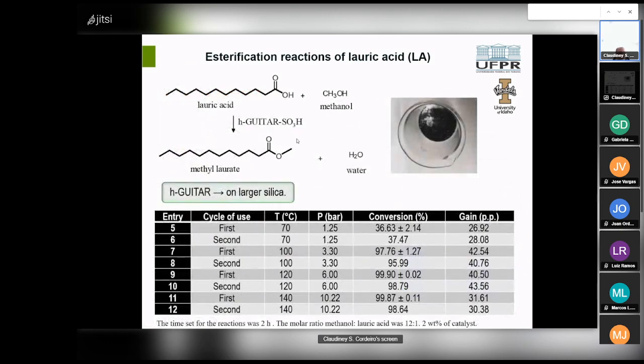After the first cycle of use, the catalysts were recovered, regenerated, and reused in a second cycle. Therefore, the experiments corresponding to the second use of the catalyst were not carried out in duplicate. The last column shows the increase in lauric acid conversion achieved with the catalyst.